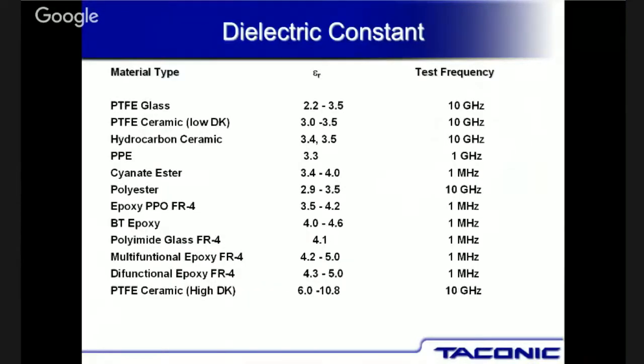So, again, what I just did here is put down all the different materials that I could think of that are being used today in the industry. And our product is basically the PTFE glass, the Taconic products. What we're doing is taking glass fabric and coating Teflon onto it, or polytetrafluoroethylene. By putting just PTFE in glass, you can see we get a dielectric constant of 2.2 up to 3.5. If we put some ceramics in it, we can change the dielectric constant from 3 to 3.5, and you also change the mechanical properties by putting different fillers in there.